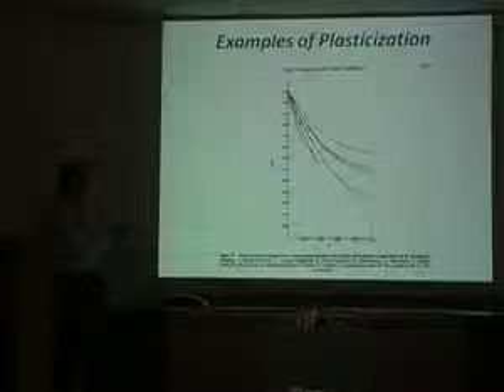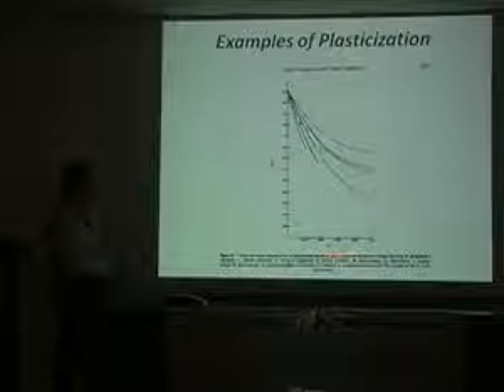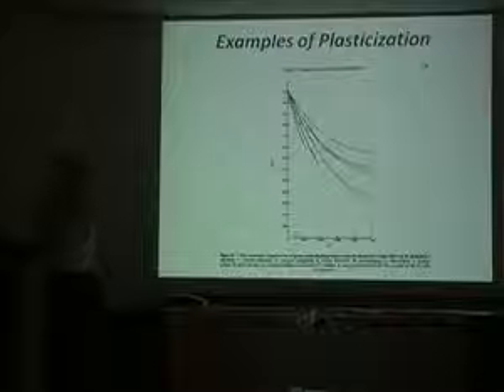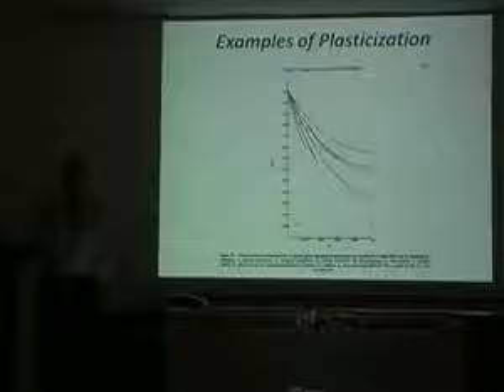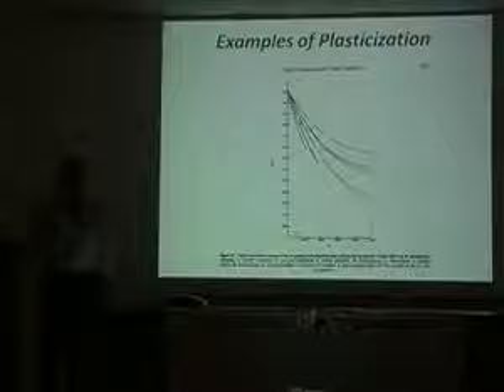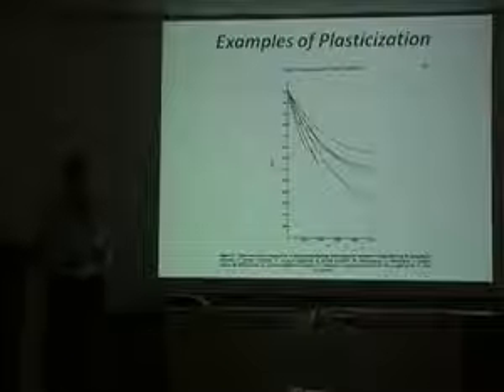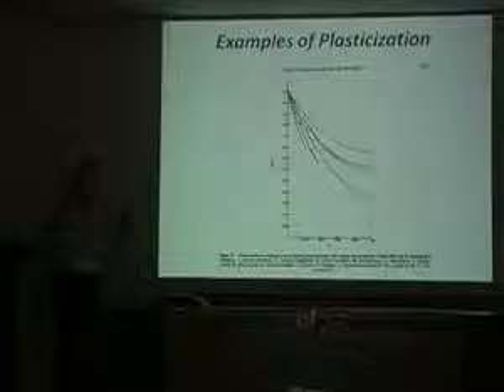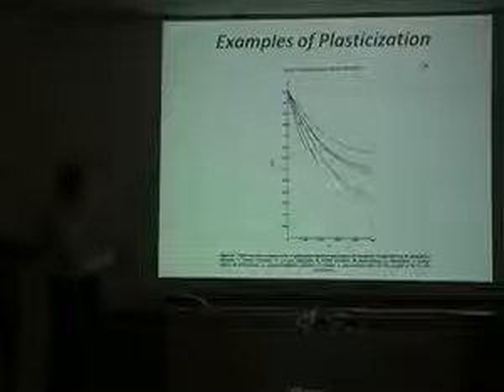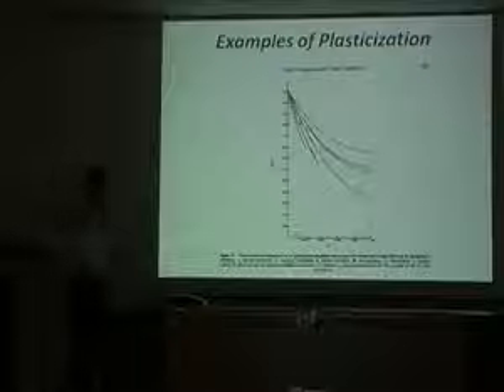This is another example of plasticization. This is the Tg as a function of weight fraction of different solvents in polymers. And of course, it's very important in polymers because if you use polymers and they are subjected to a plasticizing environment, like water everywhere, it can be a problem in their performance. Your airplane wings made out of epoxy, the Tg is affected by water. It's affected by those cleaning solvents that the airlines use, or de-icing solvents and things like that. So these are very important practical problems too. In this case we have a Tg change of about 140 or 150 degrees, the biggest there, depending on the solvent.